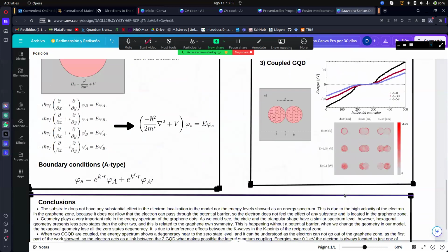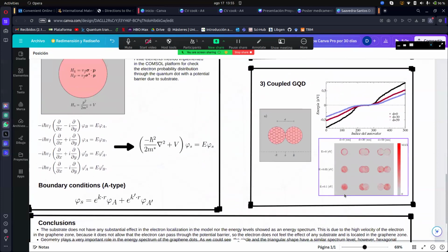As the next step, we studied the lateral coupling between two graphene quantum dots and its effect with an infinite potential at their boundaries, varying the distance between the centers of the two dots. Three distinct distance values were selected to study the effects on the energy spectrum and the localization of the electron wave function in the system. The results show similar behavior in terms of the energy spectrum typical of systems with relativistic velocities. However, it is noticeable that as the distance between the quantum dots increases, the energy values tend to decrease. This occurs because as the area of the quantum dot increases, in this case the distance between centers, the energy of the system decreases, as reported in the literature before.